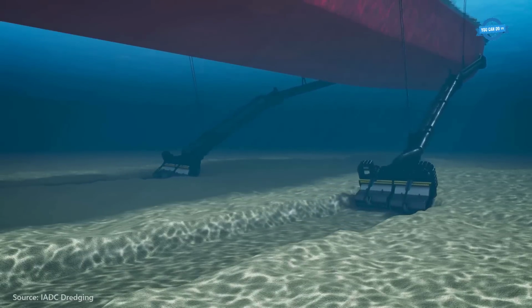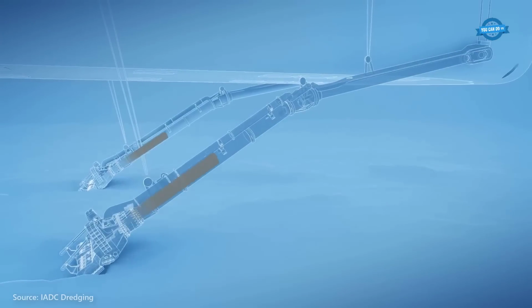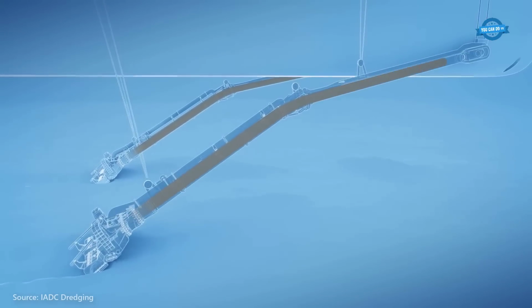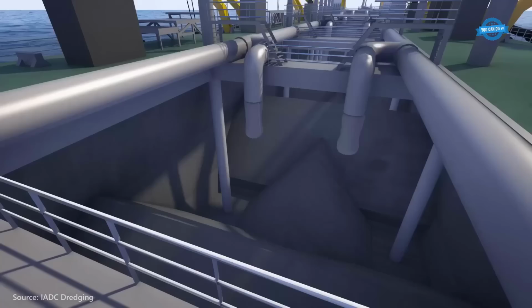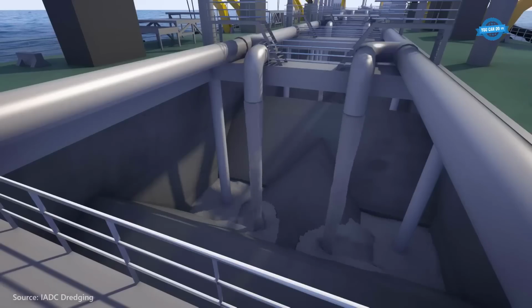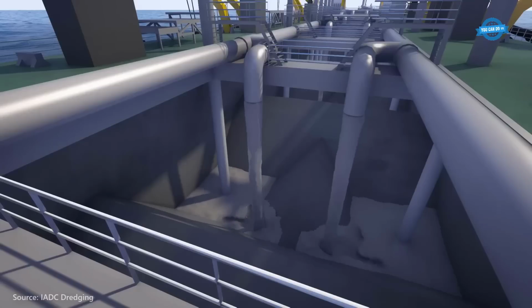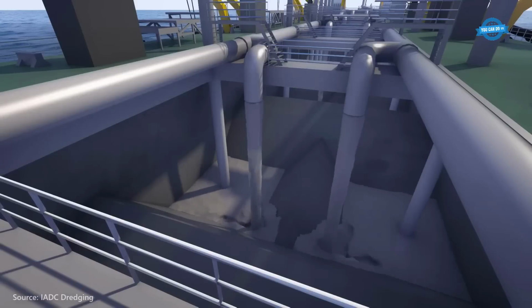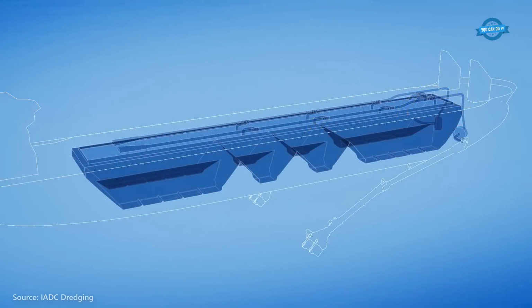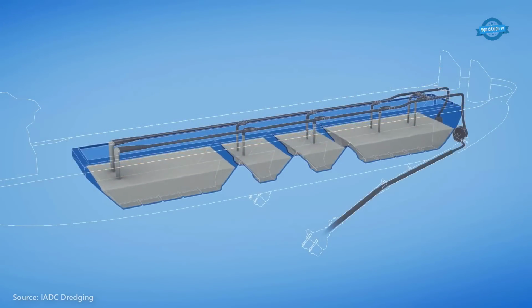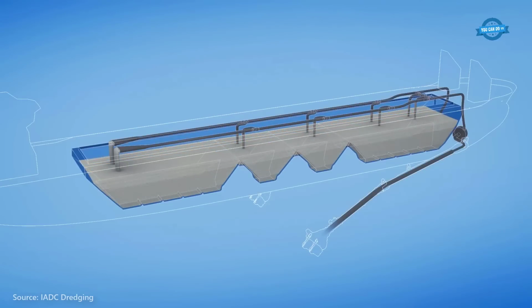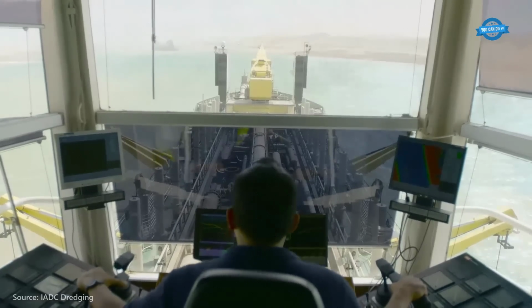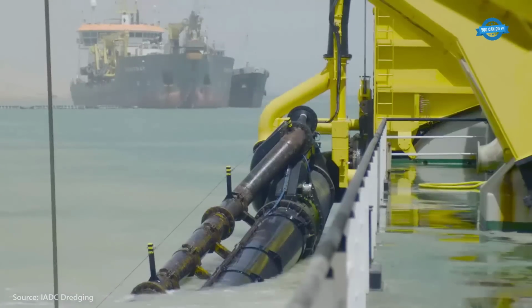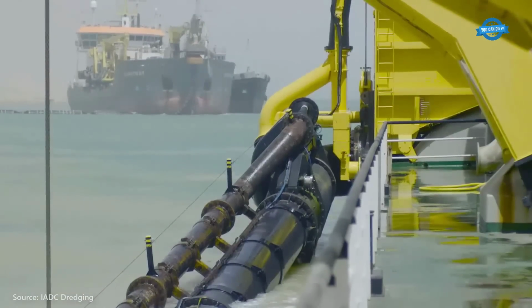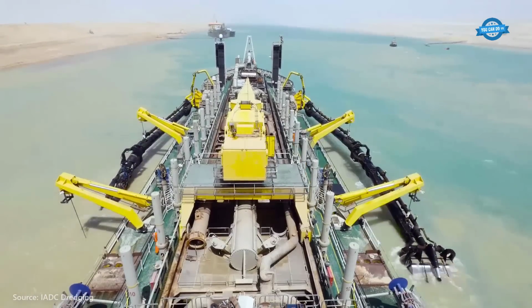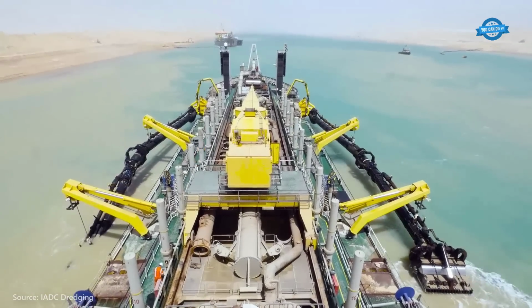As the vessel moves forward at a reduced speed, typically between 1 and 2 knots, the dragheads loosen the seabed material. Powerful dredge pumps then suction the material through the 1,000 to 1,200 mm diameter suction pipes into the onboard hopper. A typical hopper, like that of the Van Oord's TSHD Queen of the Netherlands, holds up to 35,500 cubic meters of dredged material and can dredge depths of up to 160 meters.